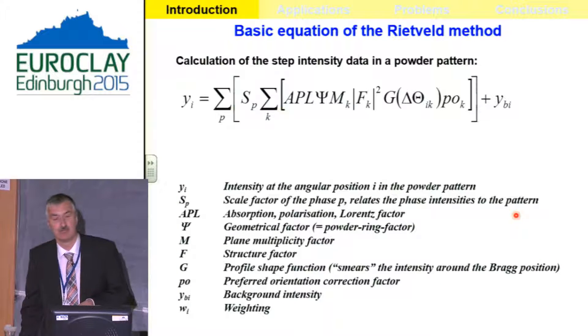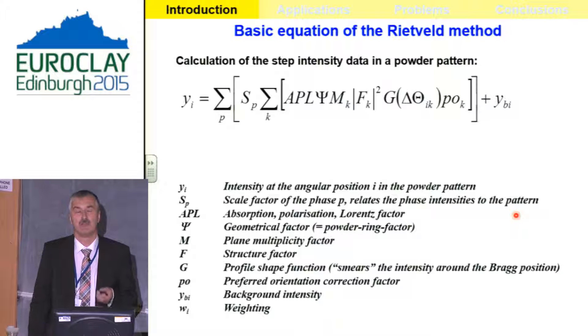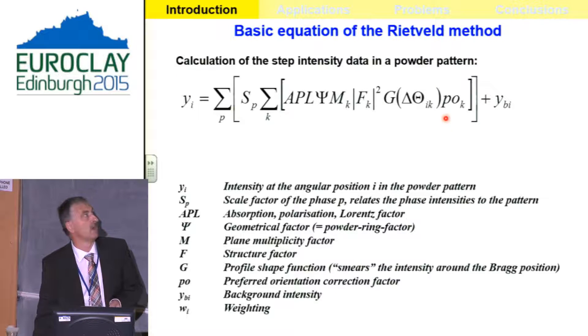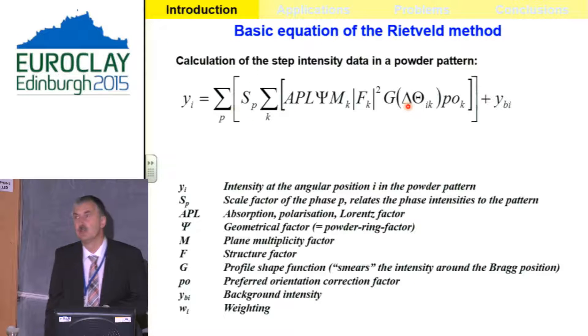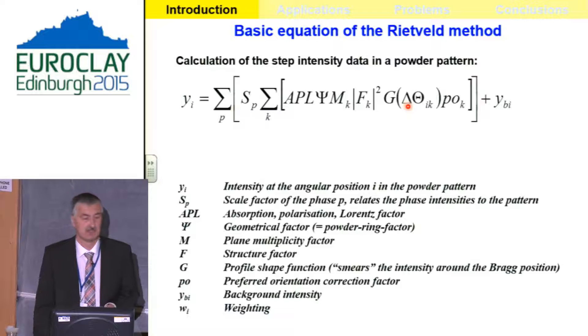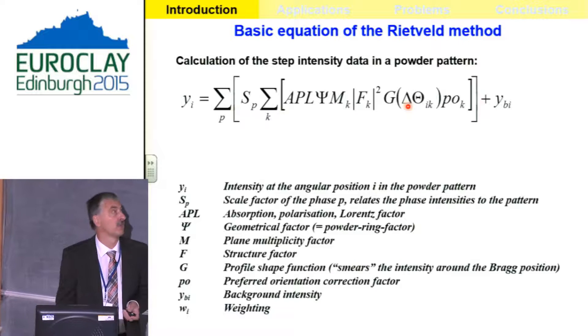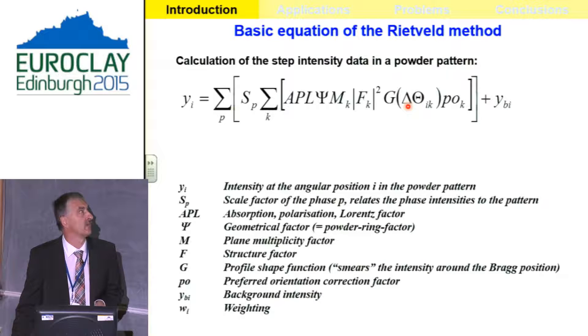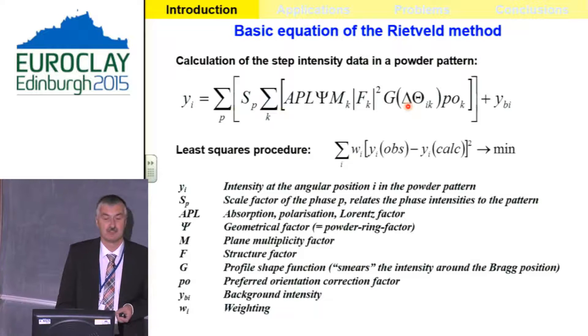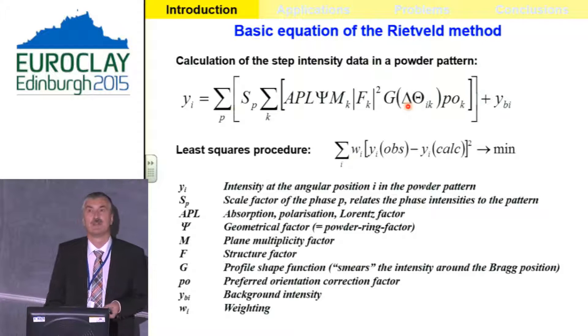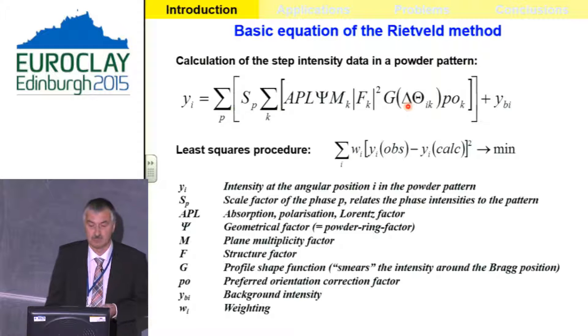The basic equation of the Rietveld method is based on the calculation of peak intensities hkl, labeled here by k. The only difference is that we are now smearing the intensity around a certain angular range by a profile function — originally a Gaussian function, which can describe the peaks very well in neutron powder diffraction. Some other corrections have to be introduced, and so we can calculate the diffraction pattern step by step. A least-squares procedure is used to minimize the differences between the calculated and measured pattern; this is a non-linear algorithm and it can be very complicated.